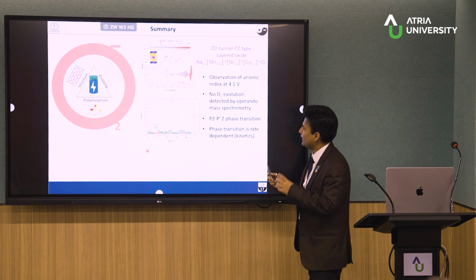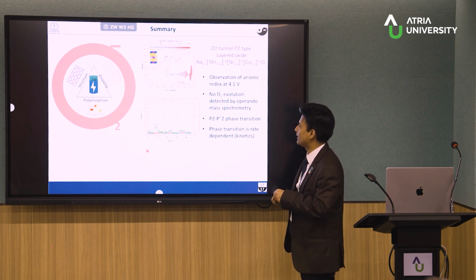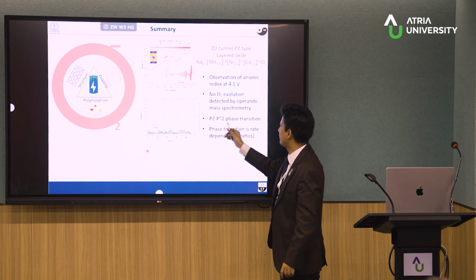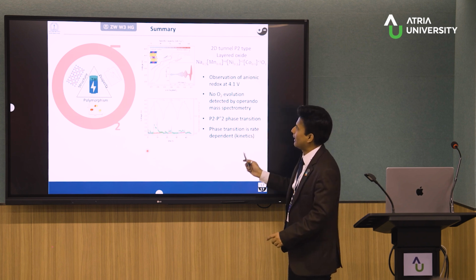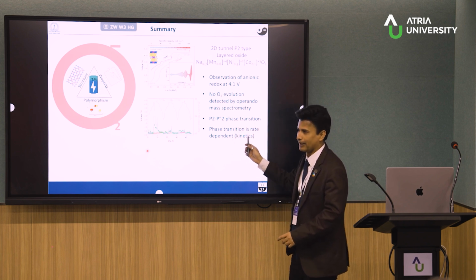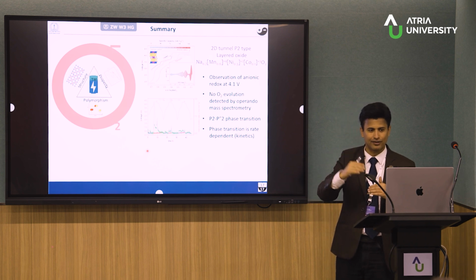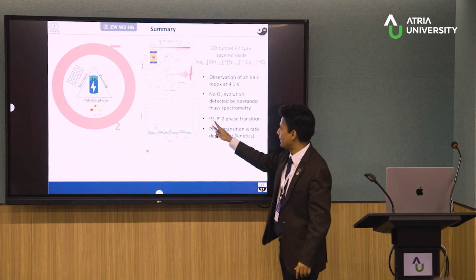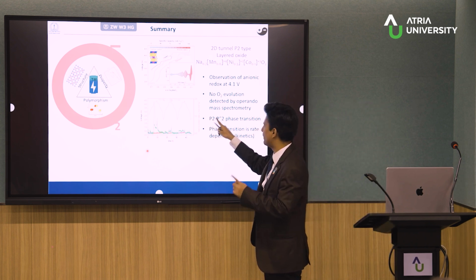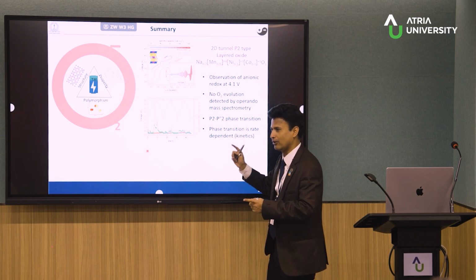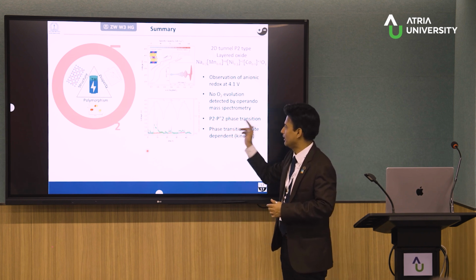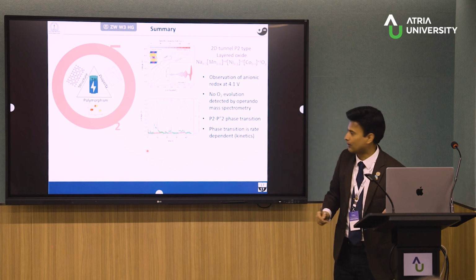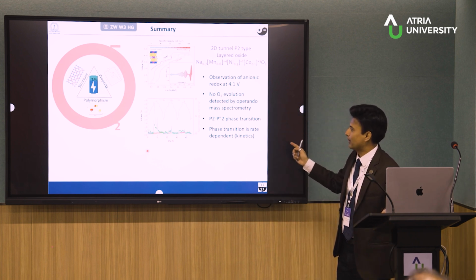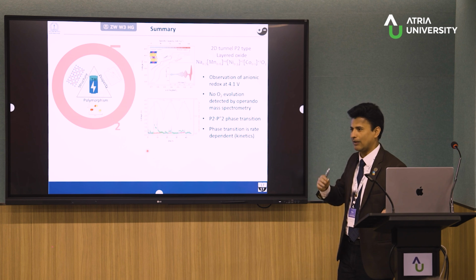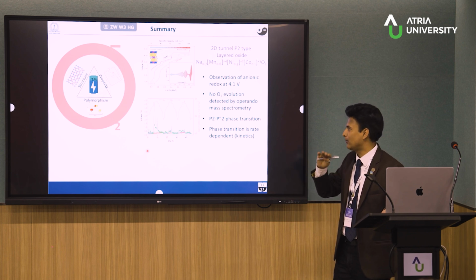And we don't see any change from P2 to O2, but we see the change from P2 to P'2 phase transition, and we find this phase transition is rate dependent. So depending on how fast or slow we charge, we will have either just P2 monophasic, or fully biphasic P2 and P'2, or a mixture of both phases. So with this, I want to conclude that this kind of anionic redox material is rate dependent. We don't have to use it at a very high rate, we have to use it at a slow rate.